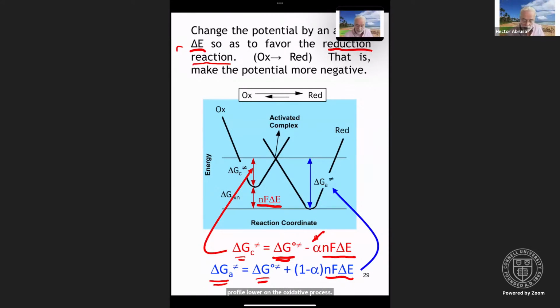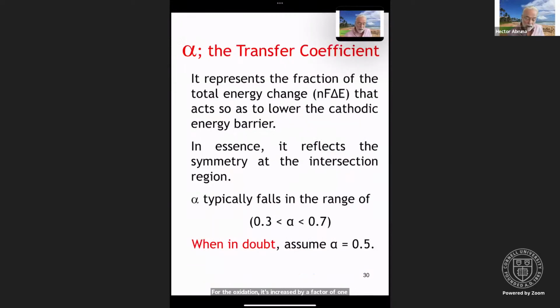And so we have that now under these conditions, the free energy of activation for the reduction or cathodic process is decreased by a fraction alpha nF delta E. For the oxidation, it's increased by a factor 1 minus alpha nF delta E. And so alpha is known as a transfer coefficient, and it's a really important idea. It basically represents the fraction of the total energy change, nF delta E, that acts to lower the cathodic energy barrier. And it's lowering by this alpha nF delta E.